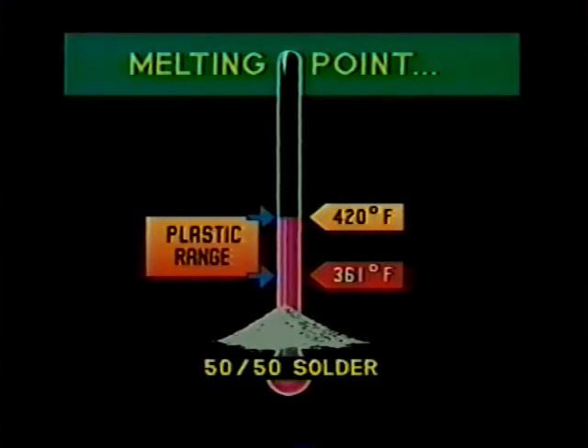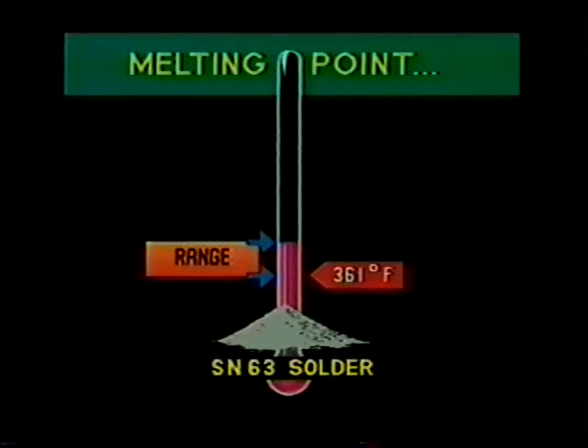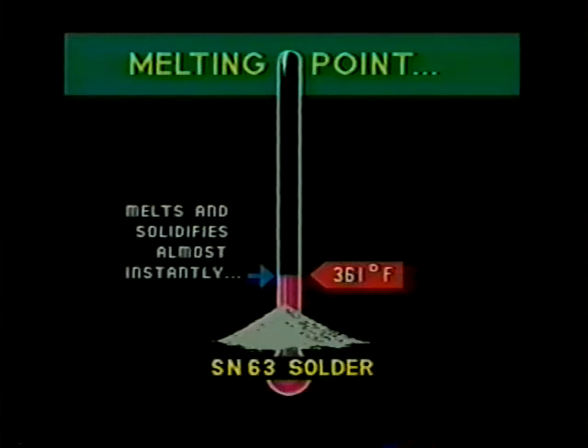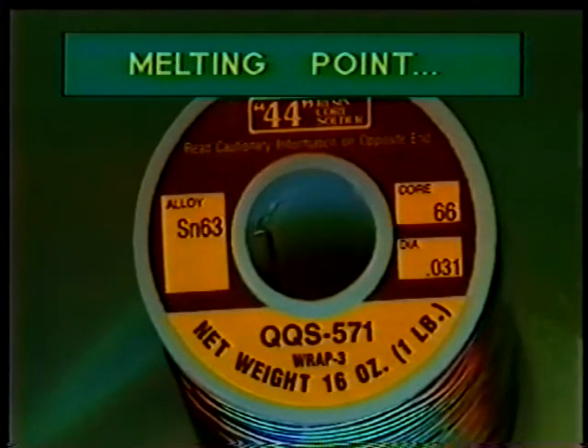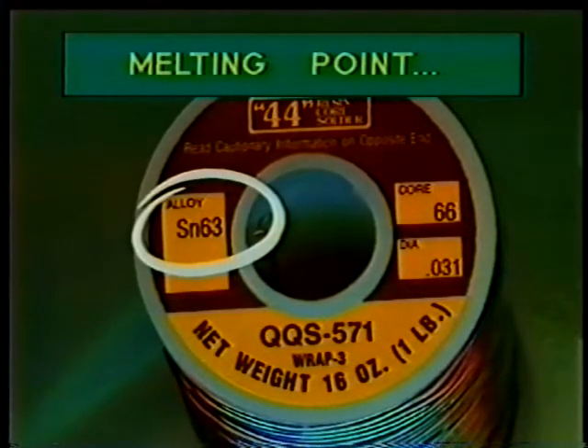A special example is the 63-37 ratio, or Sn63, known as eutectic solder, more generally referred to as Sn63. This combination has practically no plastic range, or in other words, it melts almost instantly at 361 degrees Fahrenheit and solidifies almost as fast when the soldering iron is removed from the joint. Sn63 is the recommended solder for use in electronic circuit board soldering, where use of minimal heat is necessary to avoid damaging heat-sensitive components.